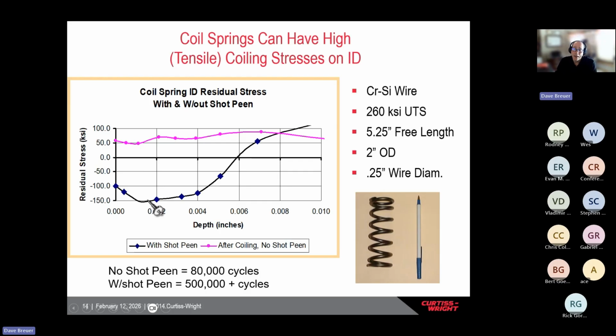And what happens from a life standpoint is with no shot peening, this spring was getting about 80,000 cycles. And then with shot peening, it goes over 500,000. As Richard says, this compression spring would fail at that ID because of these residual tensile stresses in the ID after coiling.